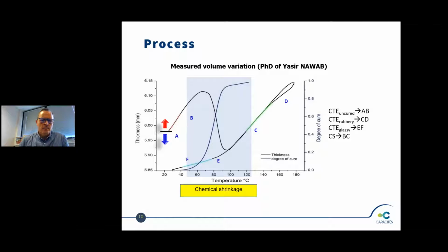And then you have a process from liquid state, the point A. You heat up your part, you let it cure, and you cool it down. So you go from A to B, from B to C, from C to D, D to E, and E to F, back at room temperature with a part which is solid. The wavy, sine curve represents the thickness of a specimen during curing.